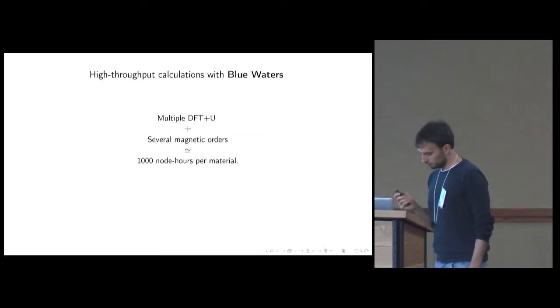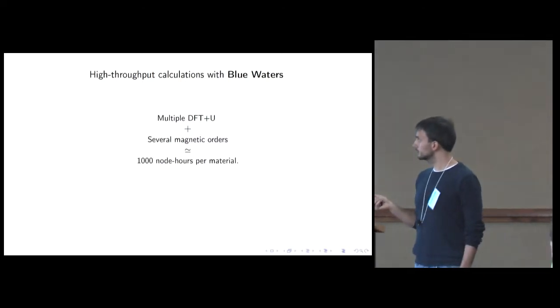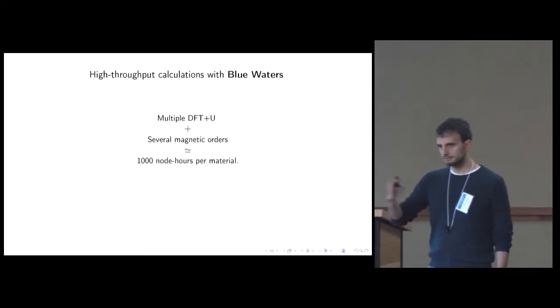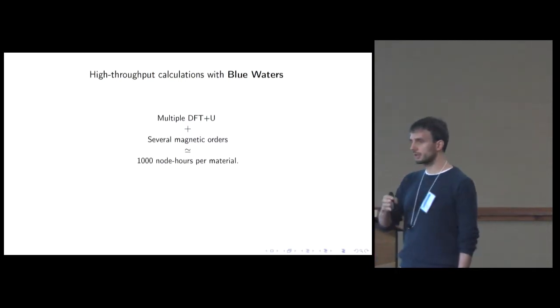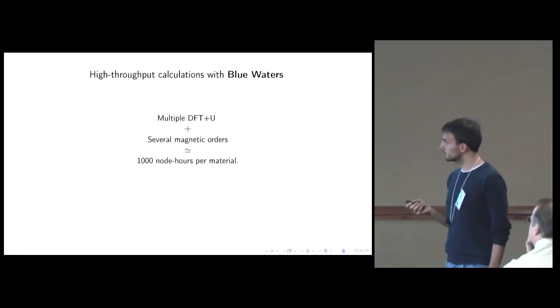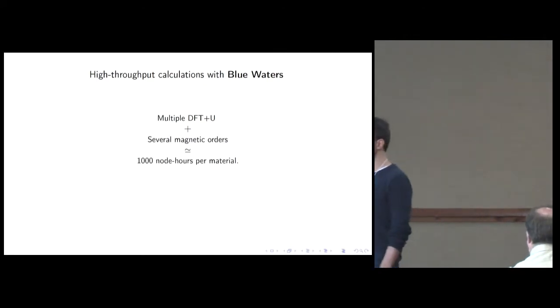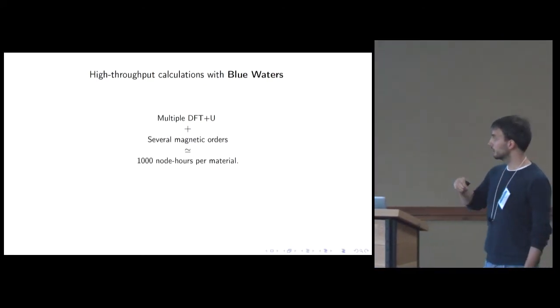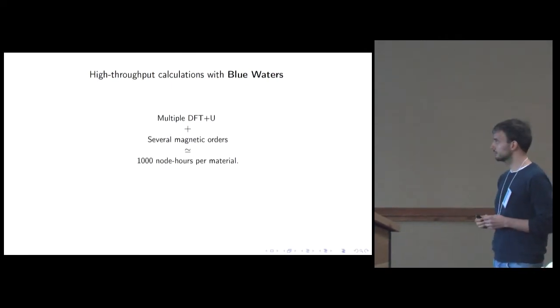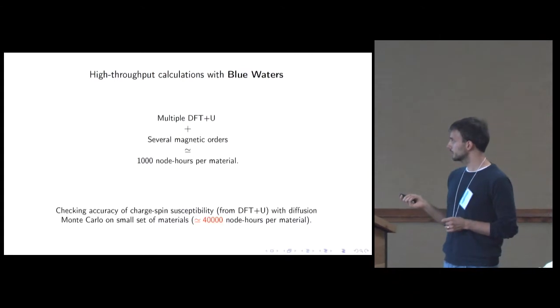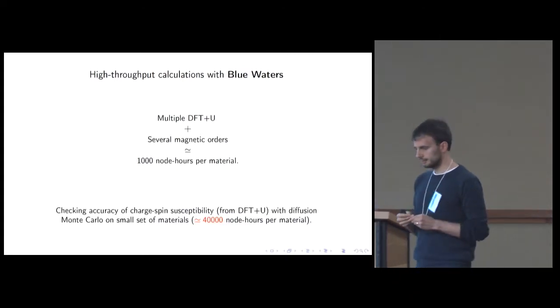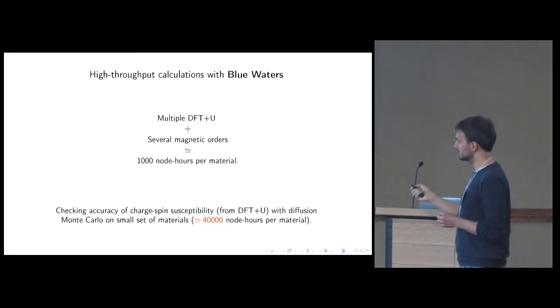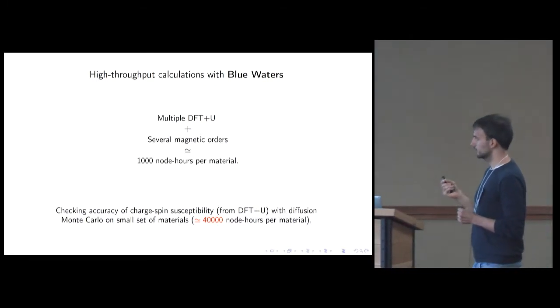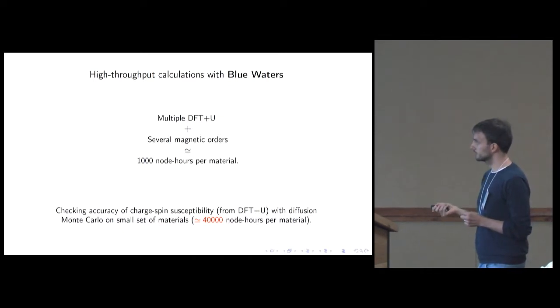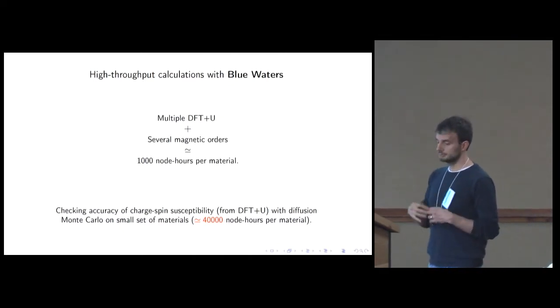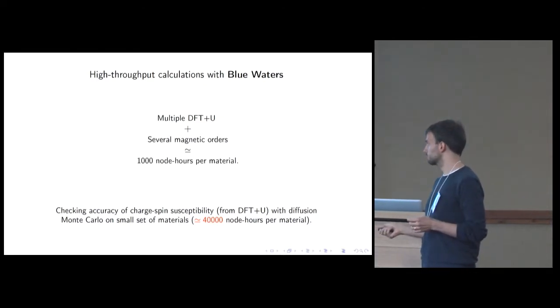Okay, we use Blue Waters to do high throughput calculations. For each material, we have to do several values of U, several magnetic orders. This amounts to 80 to 100 DFT calculations that take, on average, around 1,000 node hours per material. We have also been checking, for a smaller set of materials, whether the results that we get with this methodology are accurate enough by using a quantum Monte Carlo method that is much more accurate but much more expensive, by more than one order of magnitude.